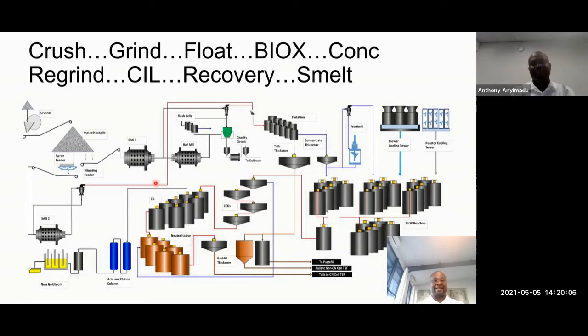So in this case, as I said, this is the existing circuit. So you follow it. It's a complex sulfide plant, which includes crush, grind, flotation, regrind of the concentrate, bacterially oxidizing the material to prepare it for leaching, and then the rest follows: the carbon adsorption and recovery, and then smelting. So that by itself is a complex sulfide ore. But I'm advocating that before you even get here, you use the material characteristics, and at the end of the secondary crushing, just split it or do something with it. Take advantage of that completely, visually different material.